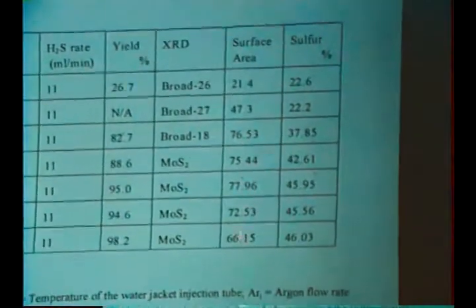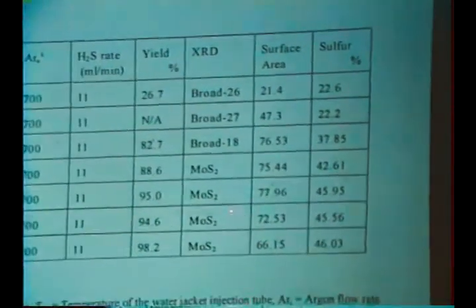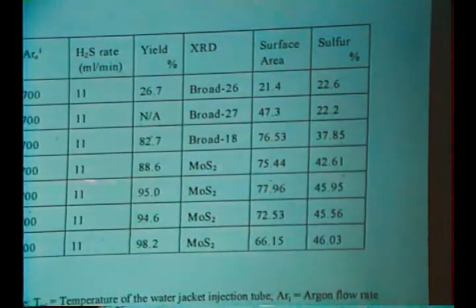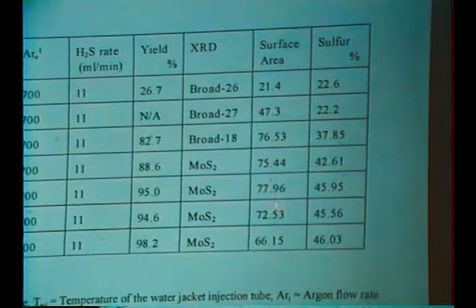And we don't see the annealing effects here that we did with the previous reactor. What we've done is shorten the heating zone by having that injector within the hot zone, and therefore the annealing effects have been reduced, giving us fairly high surface area materials at fairly high temperatures.